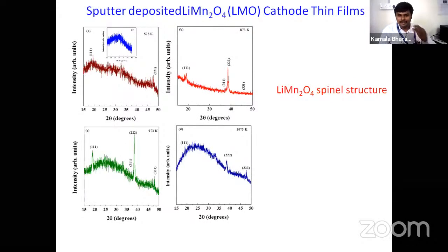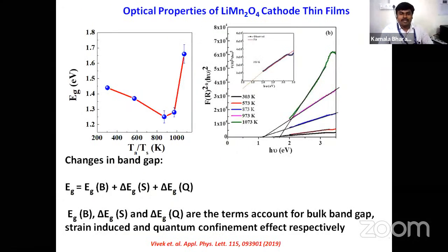So we deposit this film at various temperatures. With increasing the annealing or growth temperature, crystallinity increases, and these films are seen to form in spinel structure. Also, we have measured the optical properties like a band gap of these thin films. As you can see here, the band gap changes with annealing or growth temperature.